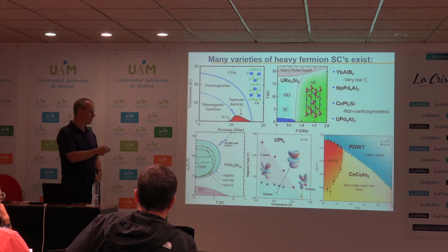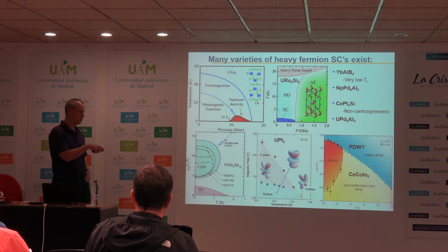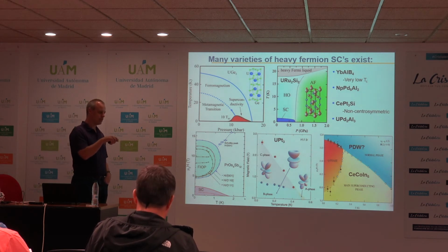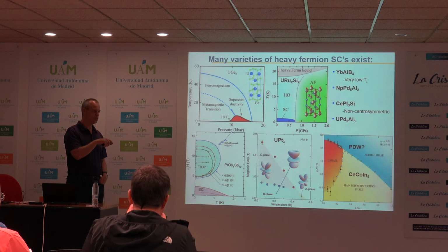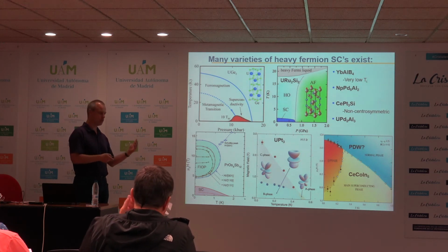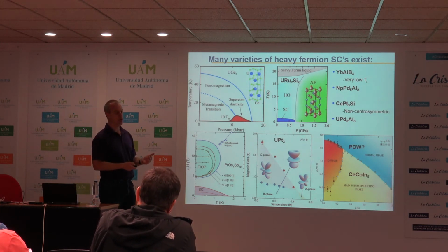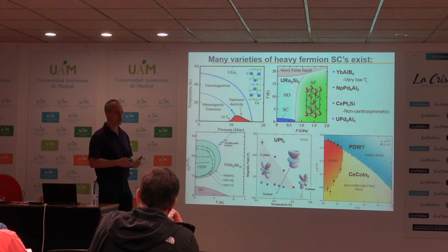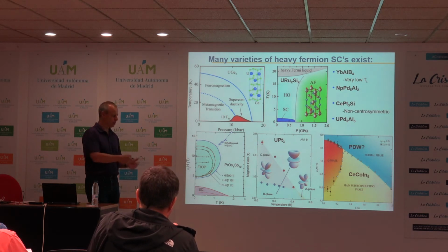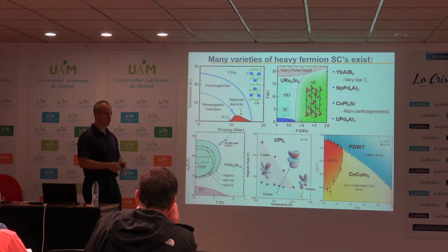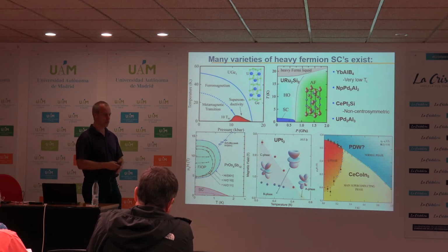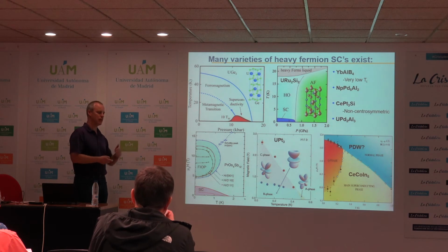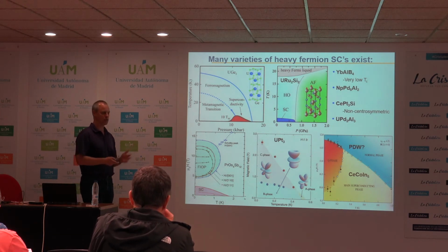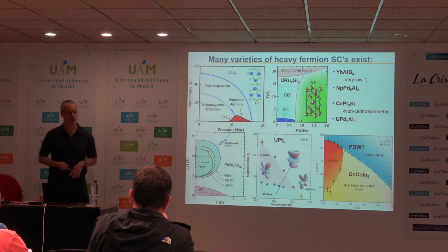It's a magnetically modulated state, and then the thermal conductivity measurements show that in fact where you anticipate the nodes to have the most nodal quasi-particles actually appear to be gapped out. And so you need an additional order parameter in order to gap out the quasi-particles. We know cerium cobalt indium-5 is a D-wave superconductor. And so in order to gap out those quasi-particles, based on the magnetic propagation vector, one explanation is to have a pair density wave to actually gap out the quasi-particles that you don't see carrying heat.